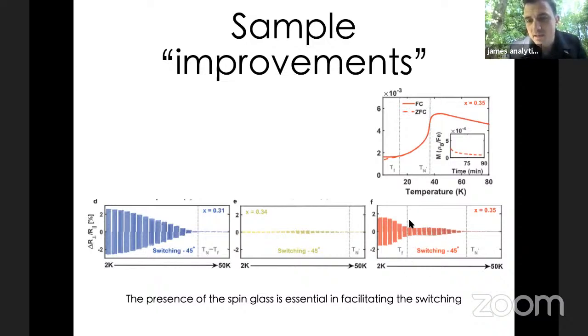What was that intermediate temperature, TF? So if you look closely at the magnetization, you actually see the zero field cooled magnetization and the field cooled magnetization split here. The reason why that's important to tell you is because the difference between zero field cooled and field cooled is that there's a different history, right? If you cool the system in a field, it has a different history than if you cool it in zero field. For an equilibrium state, where you have just a pure antiferromagnet, it shouldn't care whether you field cooled it or zero field cooled it. It's in its equilibrium antiferromagnetic state or it's not, and it doesn't know what its history was.